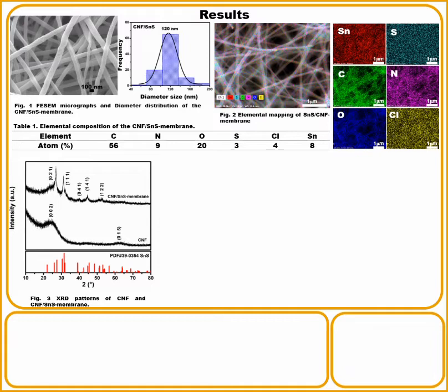Meanwhile, the carbon nanofiber membrane with tin sulfide shows 5 different peaks at 2 theta of 27 degrees, 31.50 degrees, 39.32 degrees, 44.50 degrees, and 51.08 degrees, which can be assigned to the 021, 111, 041, 141, and 122 planes respectively, corresponding to herzenbergite.